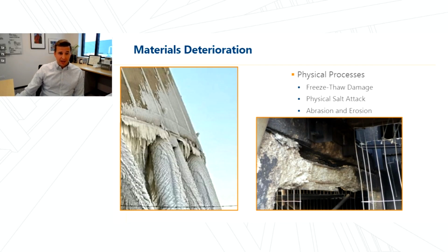We also have physical salt attack. So this is when dissolved salts build up, and when they're on the evaporative surface of concrete, they crystallize and expand when they do so, and that can result in cracking and spalling of the concrete surface and progressive loss over time. And then finally, abrasion and erosion. So many of the mechanisms that we've described can be thought of as erosive in the way that they progress, and in some cases progress from the surface. But here we're actually talking about a degradation of the concrete surface from mechanical contact. And this can occur from water flow, especially if there's particulates or an area of high agitation causing cavitation.